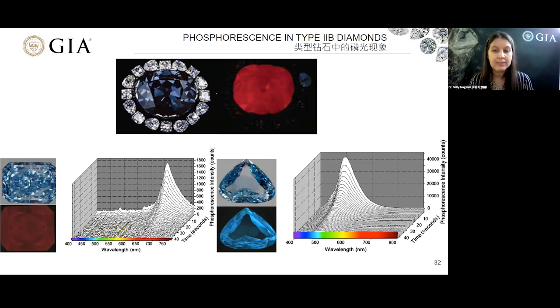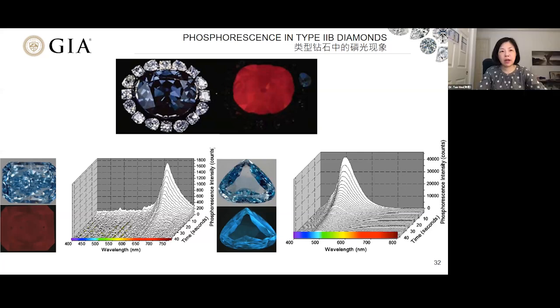a red band at 660 nanometers, like the diamond at the bottom left. Other diamonds have blue phosphorescence, like the diamond at the bottom right. 下边2张图，左边这种蓝钻发红色荧光，在它发光的时候，我们收集它的发光光谱，不是吸收光谱，就会看到大概660纳米的地方有一个发光峰，是红色的发光峰，正好在红区，你看那个彩条。右边这个钻石的发光峰在左边的蓝区，所以它发的是蓝色的灵光。